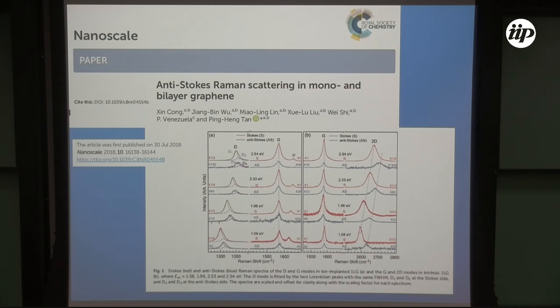The reason for that is that usually for usual temperatures, the phonon population is small, and if the phonon population is small, it's difficult to annihilate phonons. For creation of phonons, that's not an issue. So you can also use, like Juan Carlos showed us with electron microscopy, the relative intensity of those peaks to estimate the temperature of the sample. This is also done.